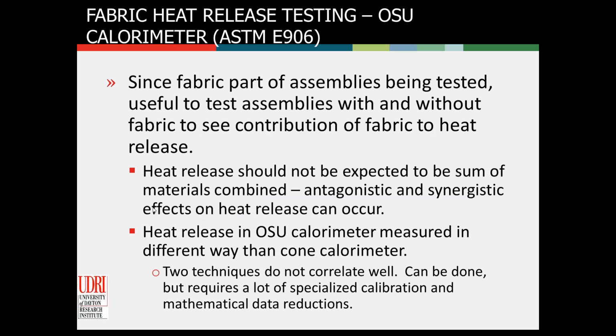So in the OSU calorimeter, you're testing that assembly. So really you're seeing the heat effects of the entire system together. And so, again, as I say here, heat release should not be expected to be the sum of the materials combined. You can see antagonistic or synergistic effects of that substrate and the fabric on heat release. And then the heat release in the OSU is measured in a little bit different ways. You can't correlate cone and OSU.